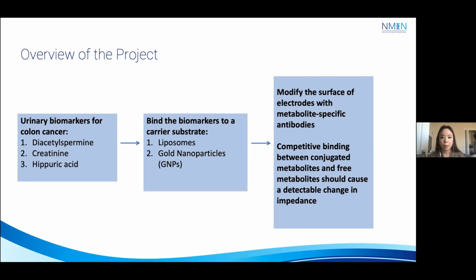And then the next step for developing the sensor would then be to modify the surface of electrodes with metabolite-specific antibodies and permit the competitive binding between conjugated metabolites and free metabolites, which should cause a detectable change in impedance due to the attachment and detachment of the conjugated nanocarriers.